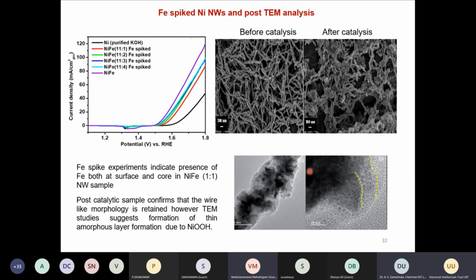Then we tried to understand whether iron is present only at the surface or at the core, which acts to improve the activity of this sample. What we have done is the iron-spiked nickel wire. That means we took the nickel wire in the electrolyte and slowly spiked different concentrations of iron into it, and see how the activity improves. Here I have compared with pure nickel, and as you can see, at different ratios of nickel to iron spike, the activity increases for the different spiked samples.